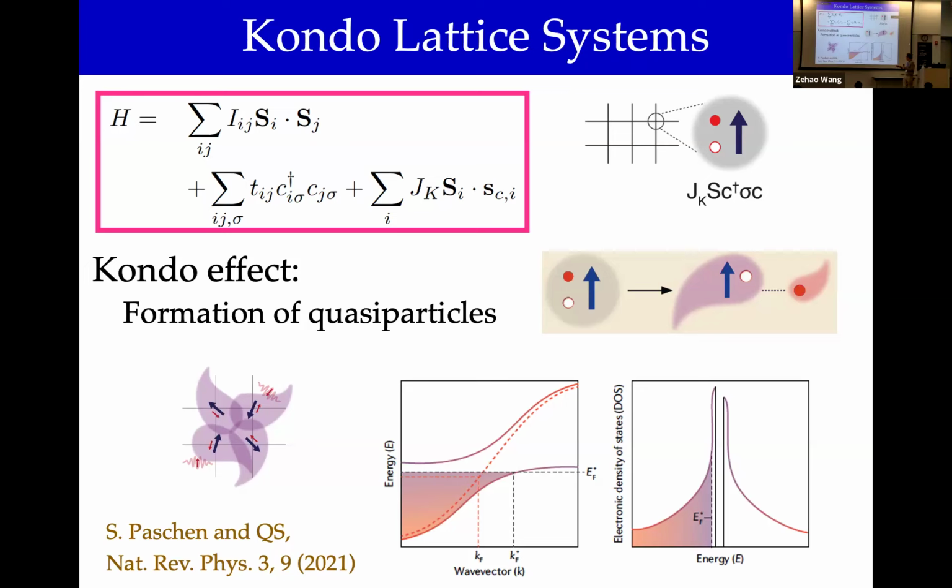the flatness of the states, single electron excitations near the Fermi energy, and also in a gigantic quasi-particle peak in the quasi-particle density of states. So these are canonical descriptions that you would encounter as the cartoons for heavy fermion states. But we should recognize these are just Fermi liquid. It's adiabatically connected to some non-interacting limit. It's an extreme case. Yes, please.